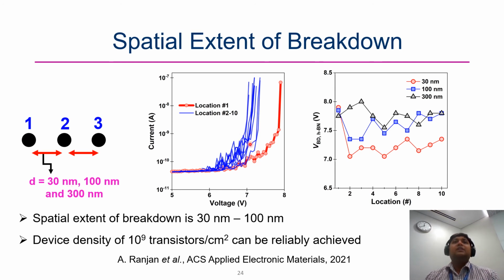And we extracted the breakdown voltage, and when we plot for all these 3 separations, we found that for 30 nanometer, you can obviously see that the first breakdown is affecting all subsequent breakdowns. But for 300 nanometer, we don't have such an effect. We can reasonably see that it's more or less randomly distributed. So this experiment helped us understand that the spatial extent of the breakdown can be between 30 to 100 nanometer under the soft breakdown conditions.